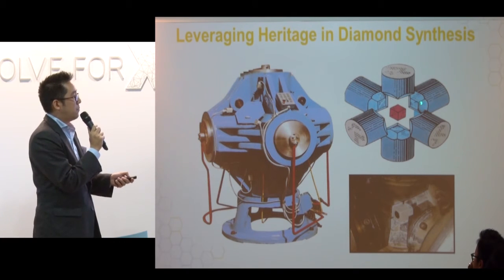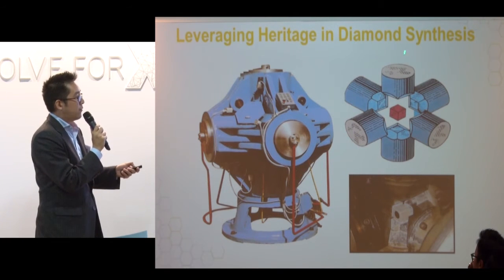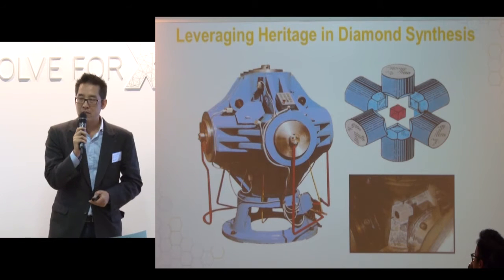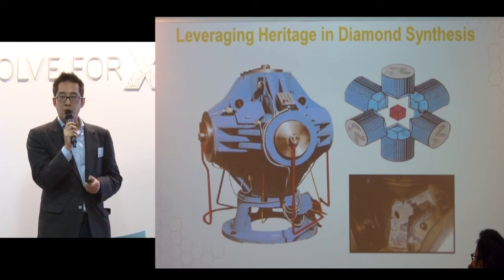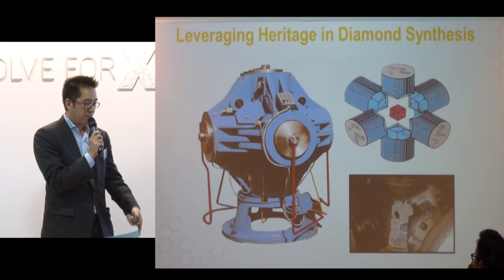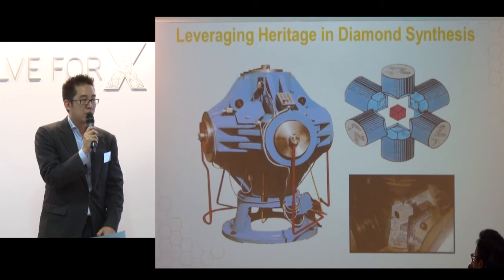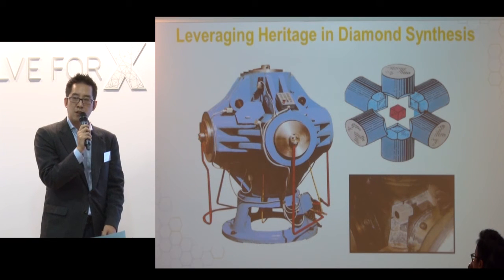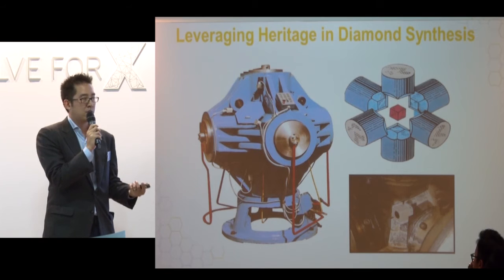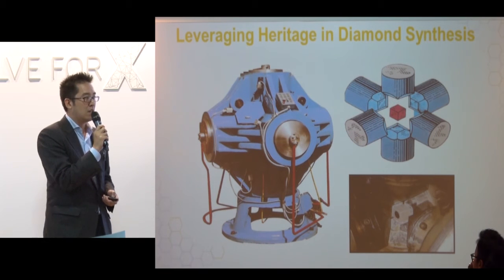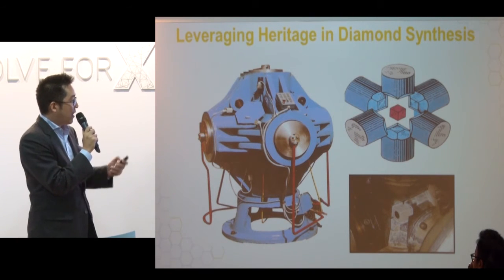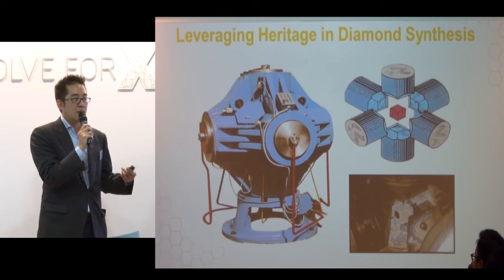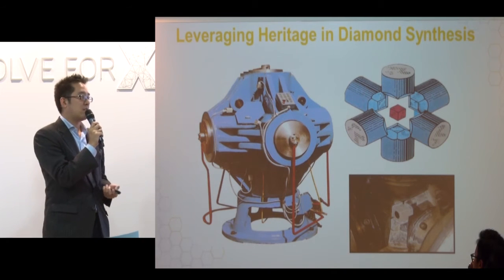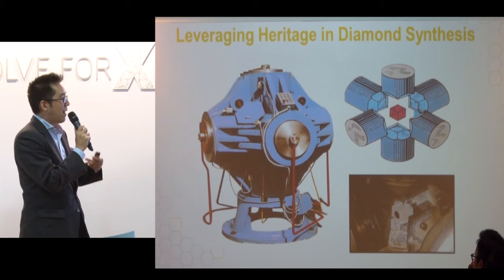And we throw in some graphite material. And if we press this at 5.5 gigapascals and about 1,400 degrees, we create an environment kind of mimicking what's similar to a couple kilometers down in Earth, and we can produce diamond, synthetic diamond. This has been done since the 60s. My father used to run GE's diamond business. They were the inventors of this technology. So this is why we have this expertise.